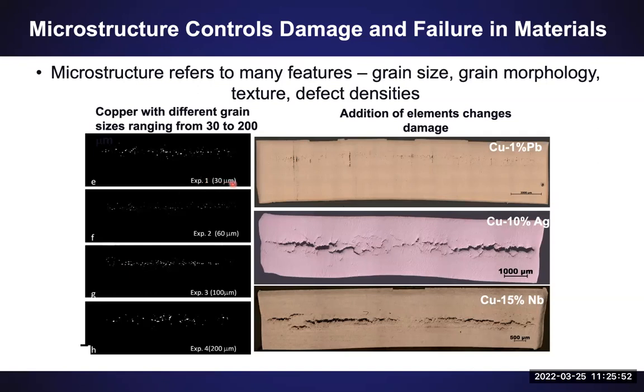This is copper, where we changed the grain size from 30 to 200 microns. The white regions in these micrographs are actually voids that nucleated in this material after it was shock loaded, and then we recovered the samples. And one thing you'll notice is if you go from top to bottom, the number of voids gets lower and the size of voids gets bigger. So we basically showed in this work that if you change the grain size of the material, you start to get larger voids, because it's easier for voids to coalesce as they're located along these boundaries.